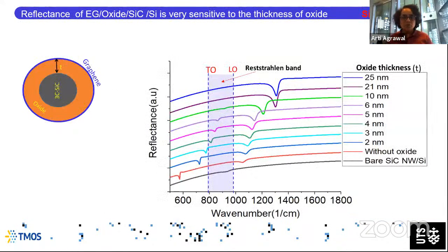This is showing you what happens to the reflectance of the structure for different oxide layer thicknesses. If you don't have any oxide, just the bare silicon carbide, you get a certain reflectance. You introduce the graphene but no oxide, you get the red curve. Then as you introduce the intermediate oxide layer, you start getting this feature here in the Reststrahlen band.